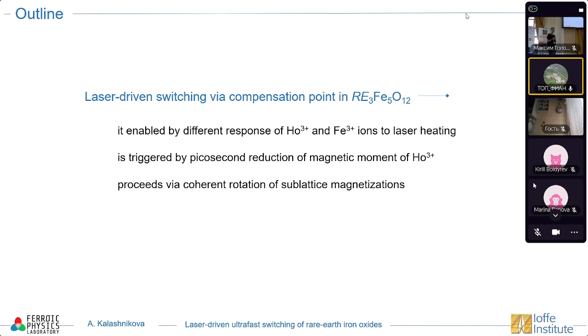Okay, there is a question online from Alexander Alexandrovsky. Is the mechanism of demagnetization purely phononic, or is there any dependence on quantum numbers of excited states? Purely phononic, yes. And dependence on quantum numbers, if I correctly understand the question, well, a very important process here is that phonons are responsible for the increase of the temperature. And then this increased temperature leads to the repopulation of the crystal field split levels in the rare earth. So in this sense, we can say that it's a change of the quantum numbers. We believe that it's like that. So phonons absorb the energy, temperature is increased, and then the rare earth reacts by repopulation of the levels.